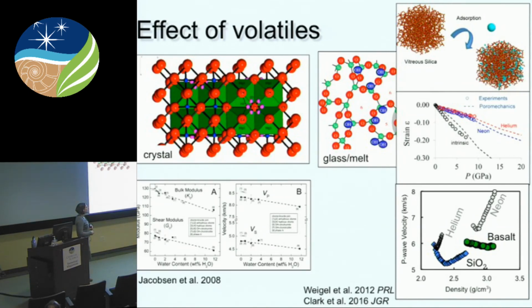We also see a stiffer response when volatiles are around for velocities. Here's P-wave velocity as a function of density, and here are two examples for silica and basalt that I've measured. The colored symbols are the intrinsic material response. When they're loaded with helium or neon, you can see that the velocities are much stiffer. Often you're getting the exact opposite response, increasing velocities instead of decreasing velocities on compression. So again, we see a different response for amorphous silicates than what we would predict for crystalline materials.